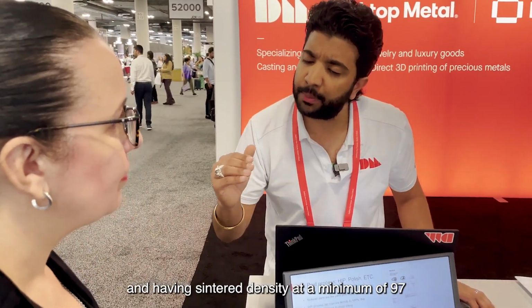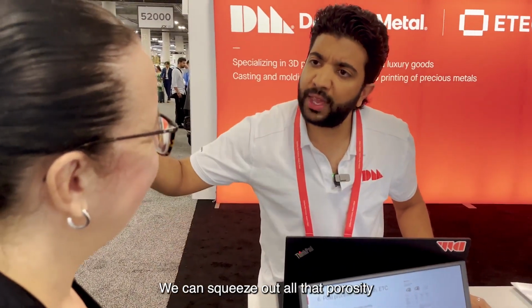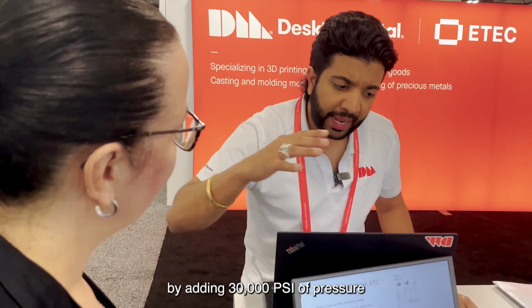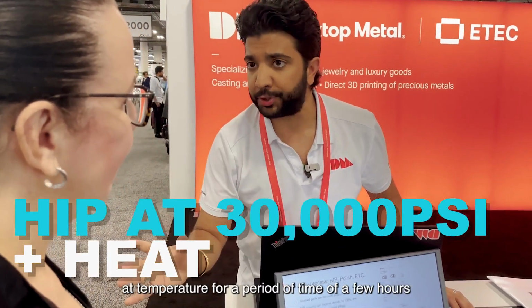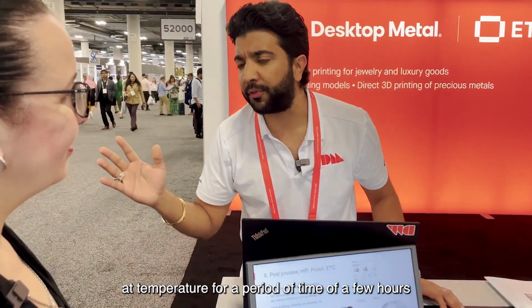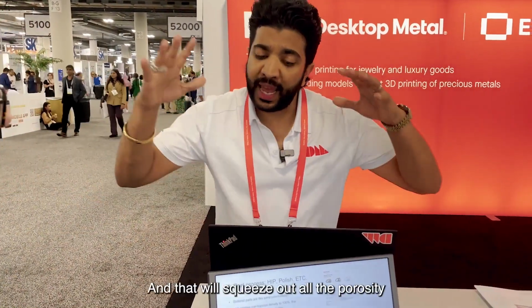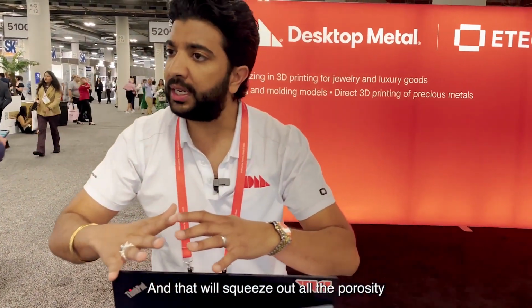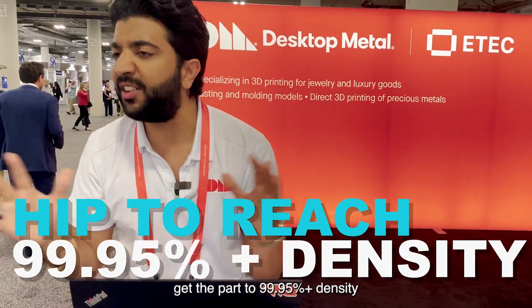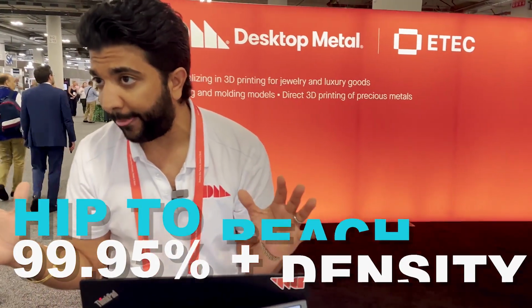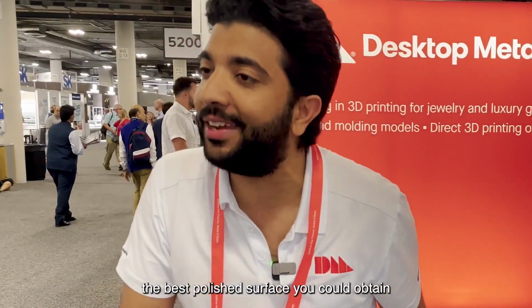When using HIP and having a sintered density of a minimum of 97%, we can squeeze out all that porosity by adding 30,000 PSI of pressure at temperature for a period of a few hours. And that will squeeze out all the porosity, getting the part to 99.95% plus density. Amazing. And then 100% dense, the best polished surface you could obtain. Fantastic, that's a dream. Yes.